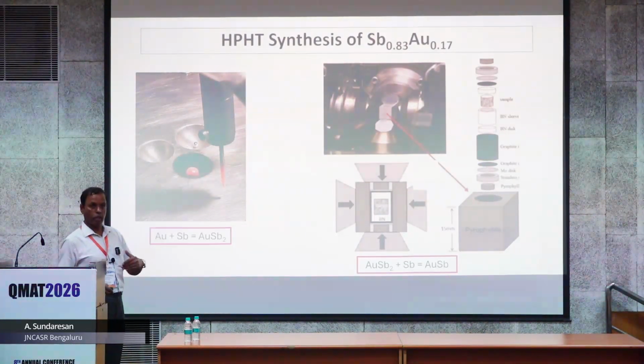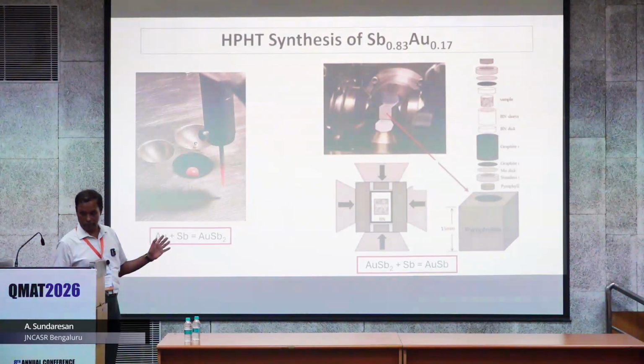You can remove the temperature quickly within 2 minutes, and then release the pressure slowly. That way you will be able to stabilize this cubic phase. So that's what we see.